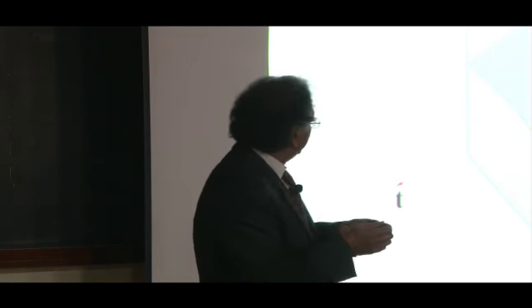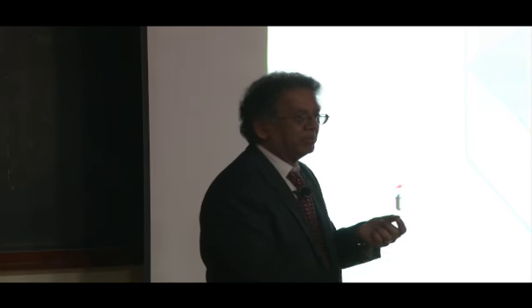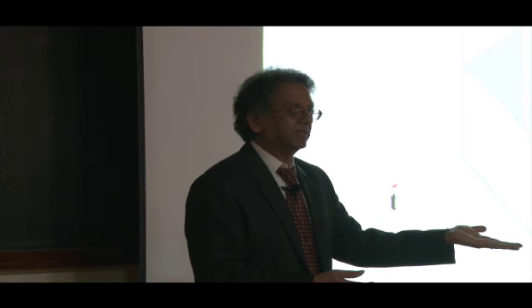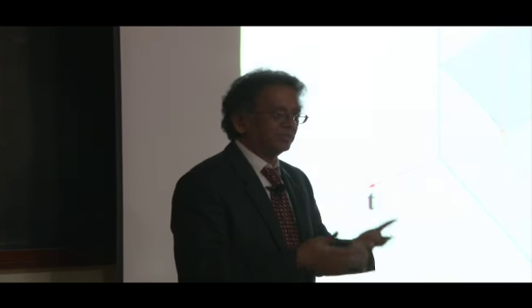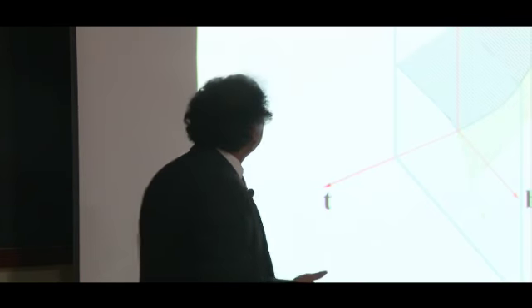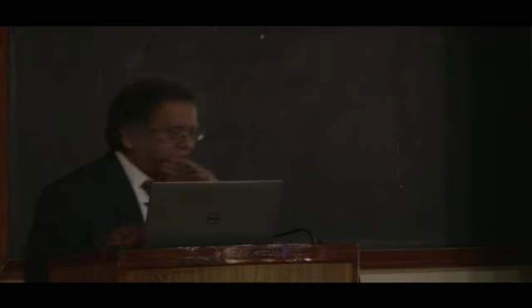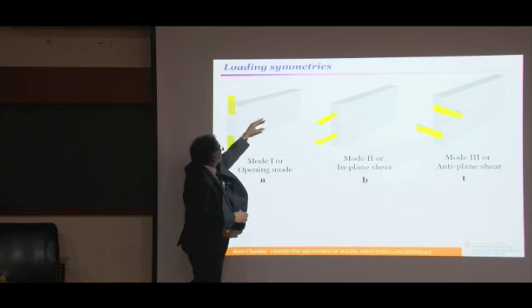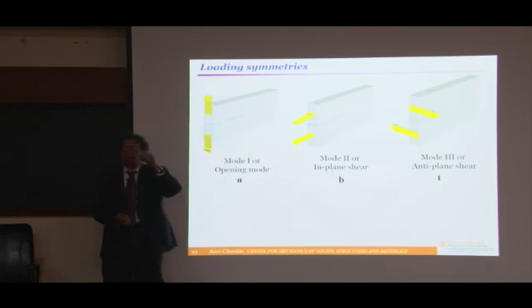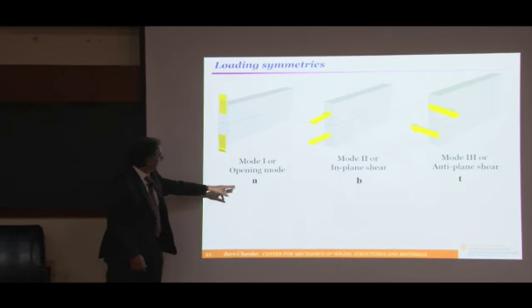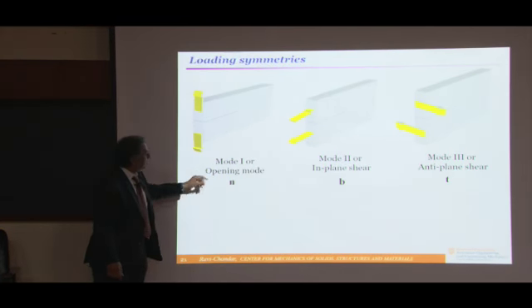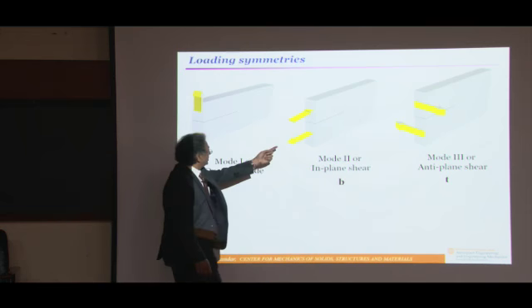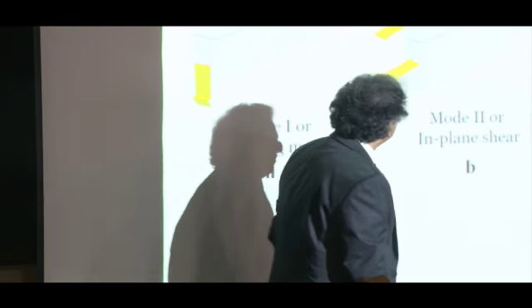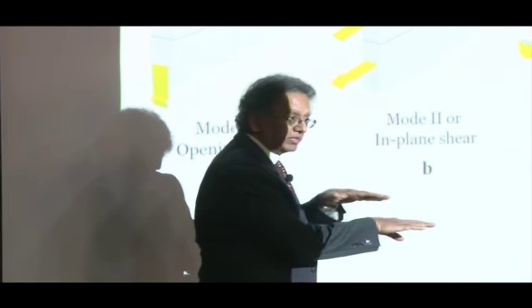Now we can read the elastic calculation done by two gentlemen, George Irwin and Max Williams. They calculated for an arbitrary crack state what would be near the crack tip. The crack field, first of all, will have the same character at the tip, and in particular that character is that the stresses go as 1 divided by square root of r, which means as r becomes smaller and smaller, the stress will become larger and larger, with an amplitude factor that we'll call K. This is called the stress intensity factor.